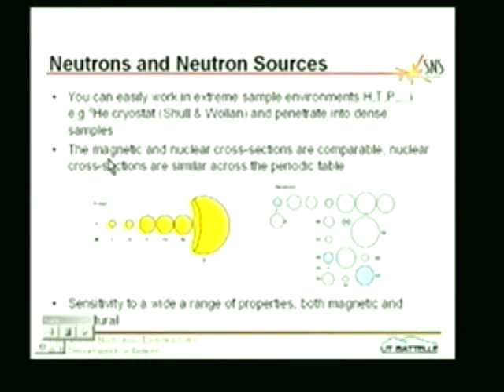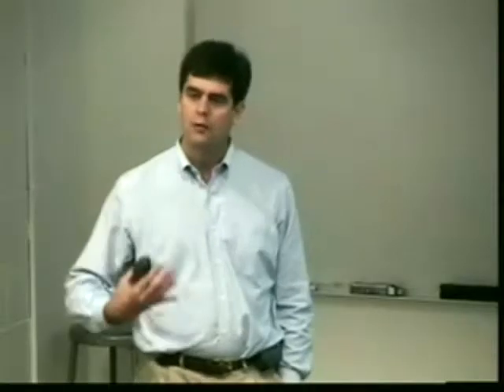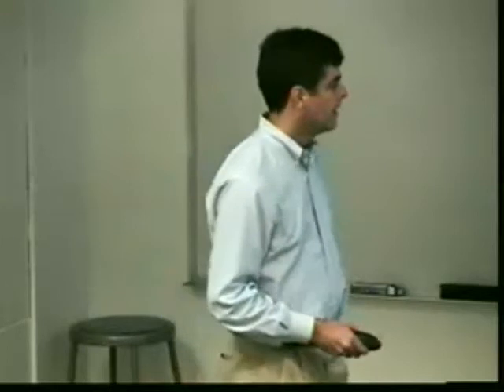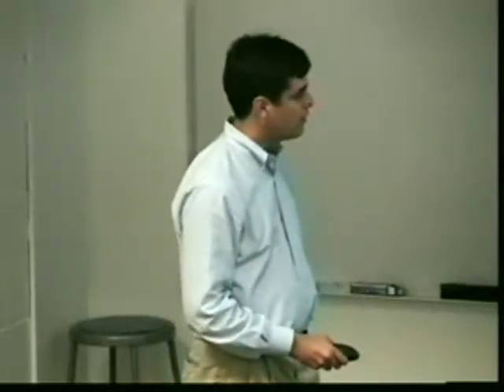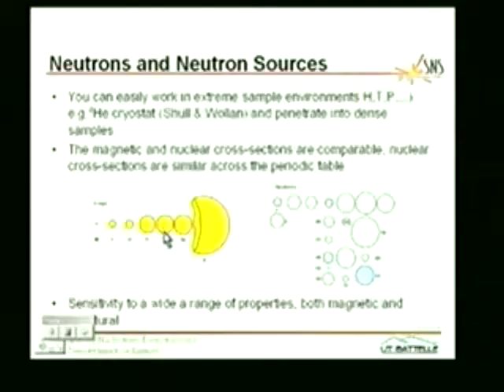And also, the nuclear cross sections are very similar across the periodic table. If you think of the case of X-ray scattering, what's shown here, starting with hydrogen, carbon, oxygen, so on down the periodic table. With X-rays, what you're sensitive to is the number of electrons. So as you go down the periodic table, the elements get more and more visible. So that means if you're trying to locate a hydrogen in the presence of, say, an iron, it's extremely difficult.